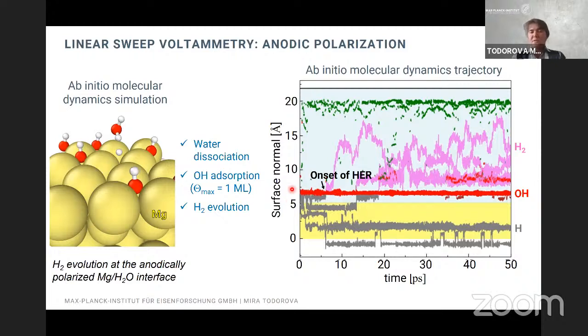We have again water dissociation initially, and we have hydrogen and OH formation. We also see that some of the hydrogen propagates throughout the water layer in form of hydronium, Eigen and Zundel ions to go to the other side of the cell in order to screen some of the potential. We also see the onset of several hydrogen evolution reactions. So they are shown here in purple.